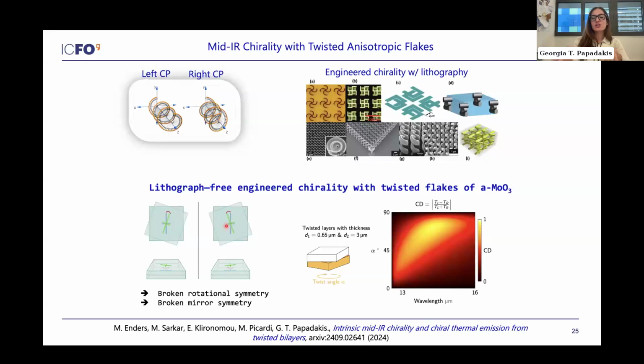So what we did instead is we considered just 2 flakes of molybdenum trioxide, one on top of the other, that are twisted with respect to each other. And if you look at this configuration, it breaks rotational symmetry and it breaks mirror symmetry. So it is actually intrinsically chiral. So here's a simple calculation where by changing the angle, the twist angle between the 2 flakes, you can see that, again, within the frequencies where you have this very strong absorption peak and these Reststrahlen bands, the circular dichroism of this device actually goes up to 1, which is very unconventional.